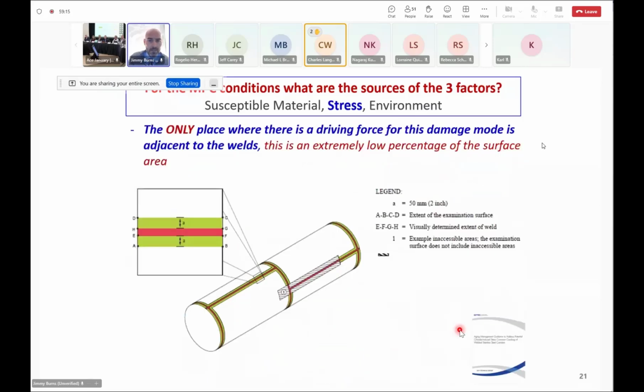What does that mean? Well, if we look at where those locations are on the component, the only place that there's a driving force for this CISCC damage mode to happen is going to be directly adjacent to these welds, because there is not a stress that can drive this damage mode anywhere else besides directly adjacent to the welds. Okay, and I think we just talked about how big these components are. This is an extremely low percentage of the surface area.